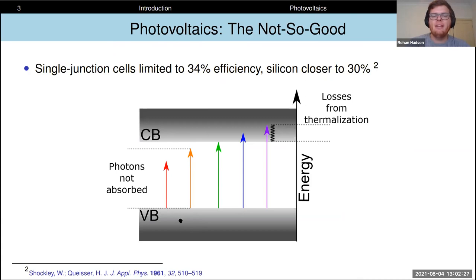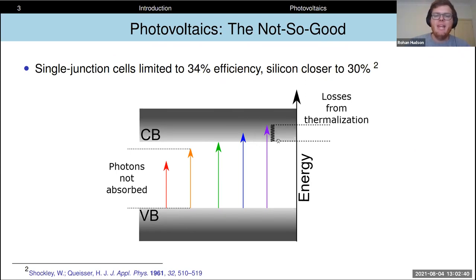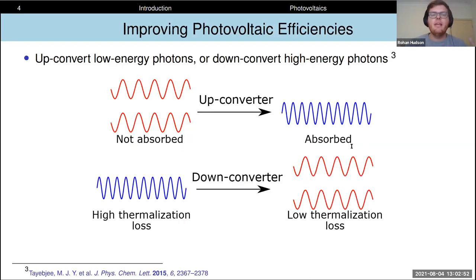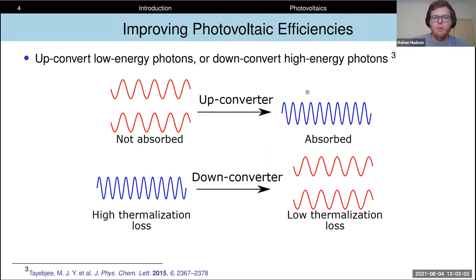For a single band gap semiconductor, some fraction of the solar spectrum has photons of energy less than this band gap which can't be absorbed by the semiconductor. On the other hand, photons of energy higher than this band gap can be absorbed, but any energy in excess of that band gap is wasted through rapid thermal relaxation of these excited electrons to the band edge in a process known as thermalization. So there are a lot of research avenues open into trying to improve solar efficiencies, and two of the big schools of thought use methods of up or down conversion.